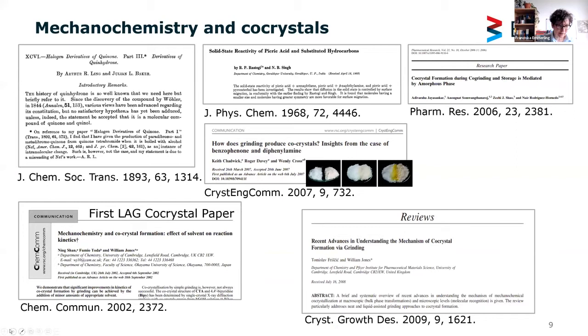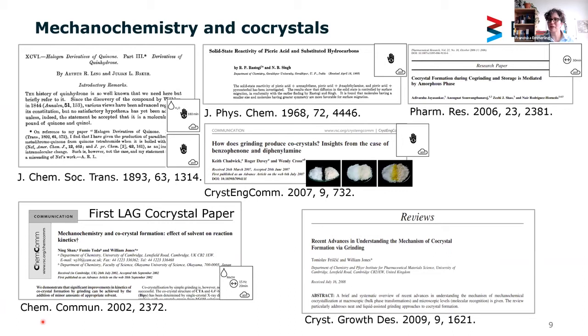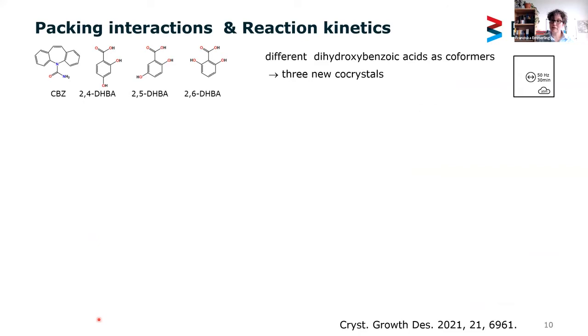Okay, let's move into details, not without showing you that all these reactions, of course, can be explained by this symbolism I showed before. So in a recent publication here, we studied the co-crystallization of carbamazepine with different benzoic acids. And we used these different acids as co-formers. You can see here again the milling condition. It's a normal ball mill, and we milled the reactants for 30 minutes.